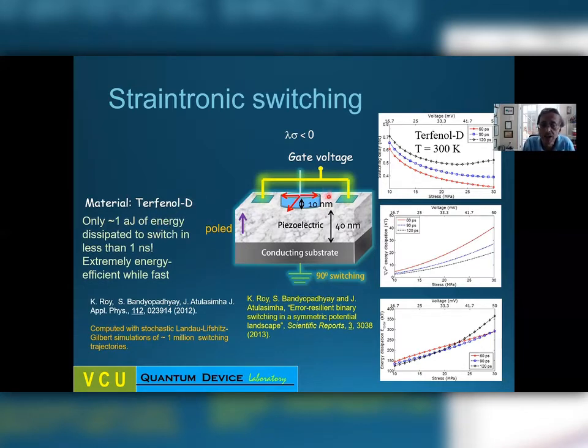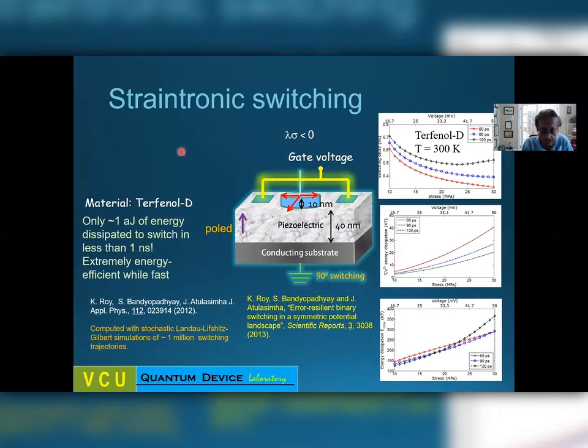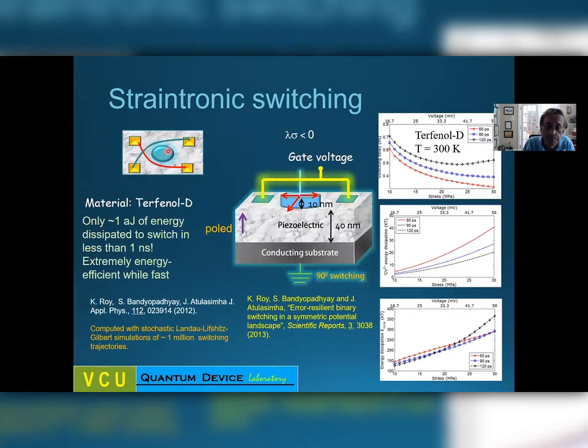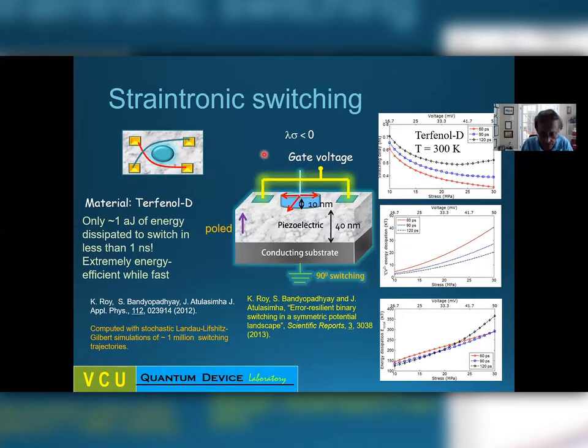There is one disadvantage: you have to pulse the stress correctly. If you overshoot or undershoot, it will not work. But there is another way where you don't have to time the pulse correctly. If you have a configuration with four contact pads where the two antipodal contact pads are shorted together, you first activate one pair to make the magnetization rotate to an acute angle, then activate the other pair to rotate it an additional acute angle, then let go and the magnetization flips. This does not require precisely timing the pulse, but the price is a larger area with four contact pads. The theory was published in Applied Physics Letters and the experimental demonstration was in Nano Letters.